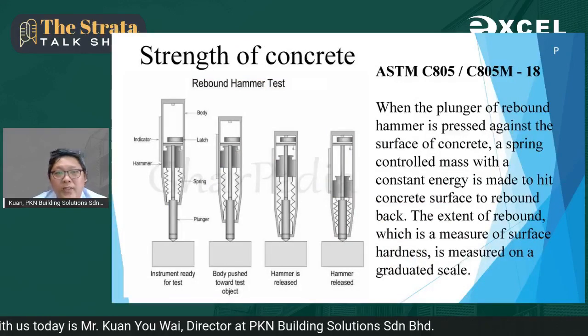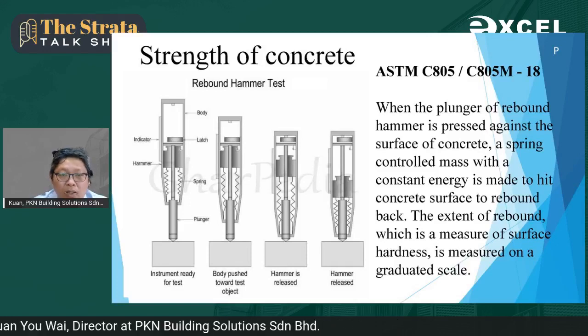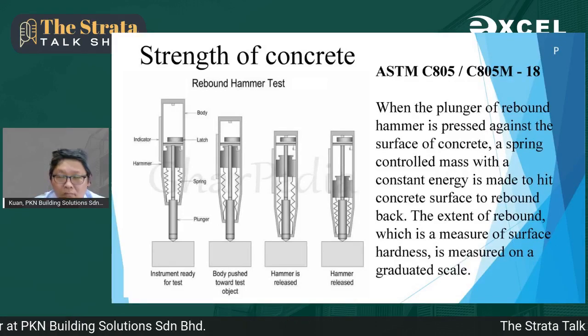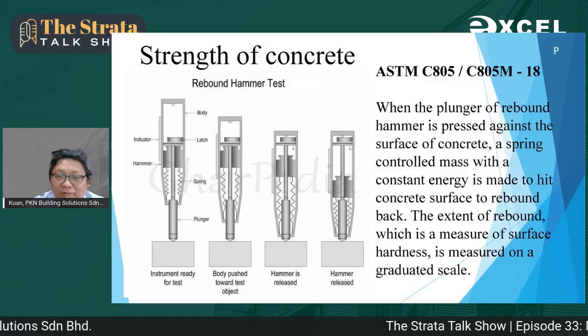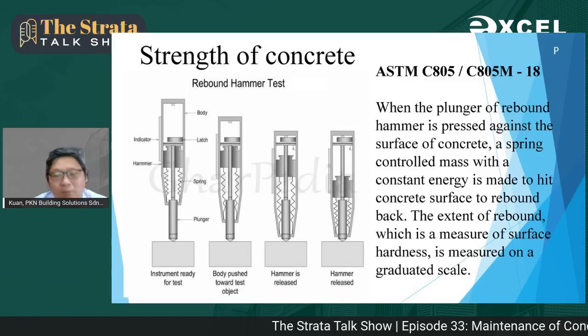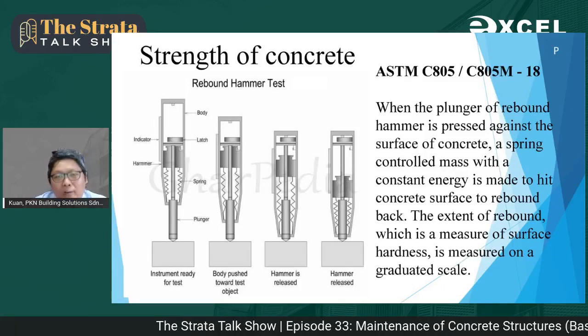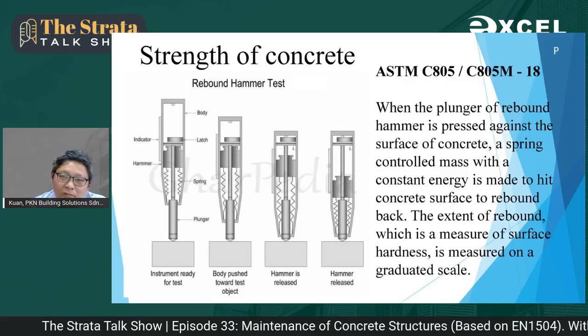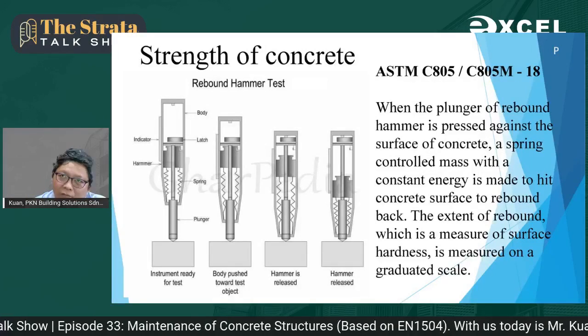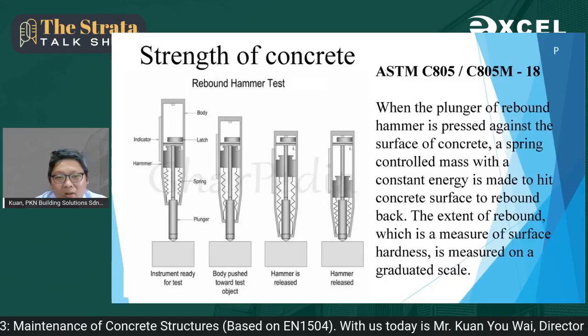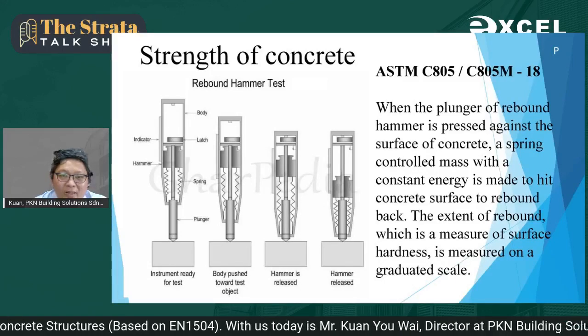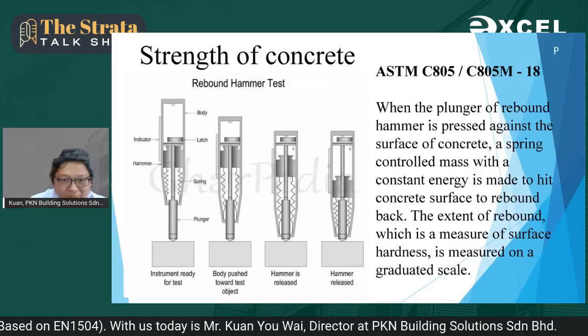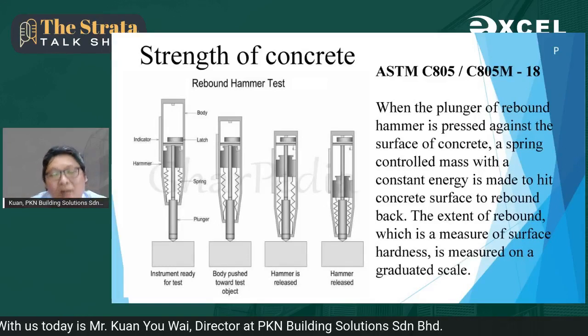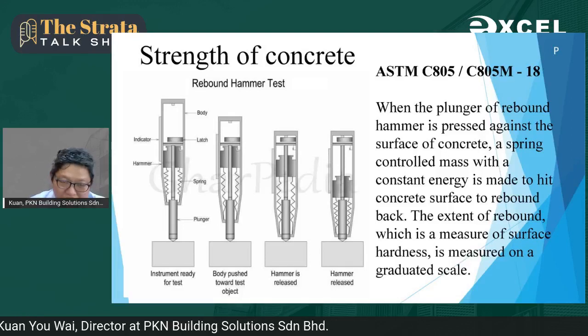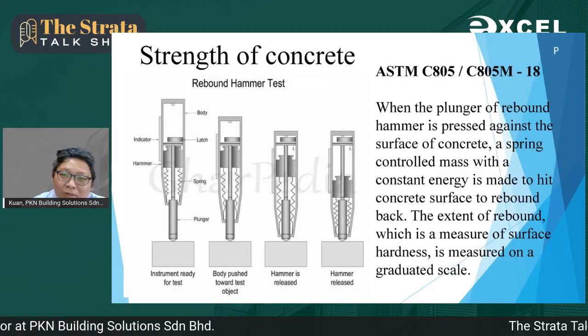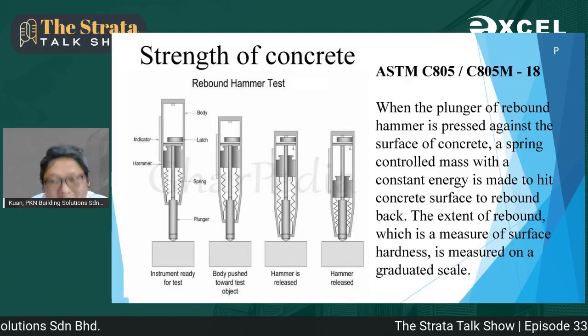The rebound hammer is an in situ method to find out the compression strength of the concrete. But the weakness is it always gives a higher reading, about 50 to 60% higher than what the concrete actually possesses if you do coring and send it to the lab for compression testing. Simply because when we hit the concrete, sometimes we hit concrete with a reinforcement steel bar right below it.